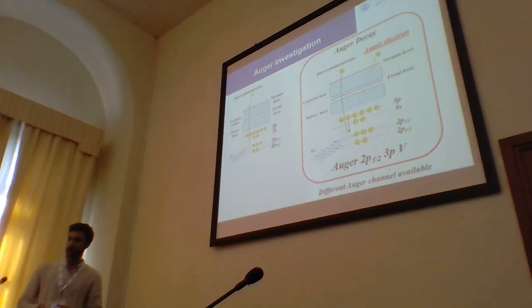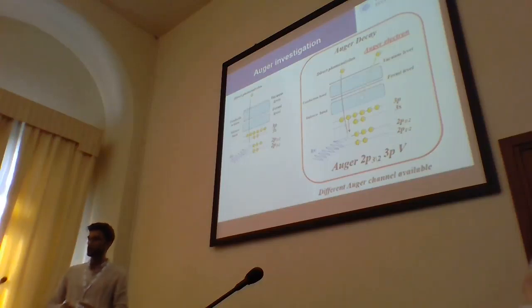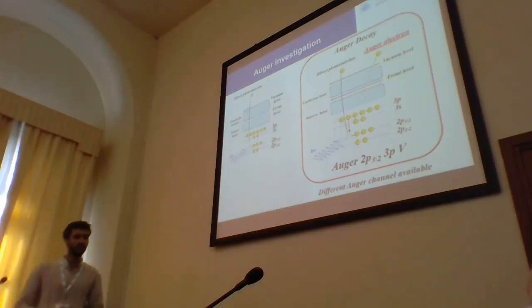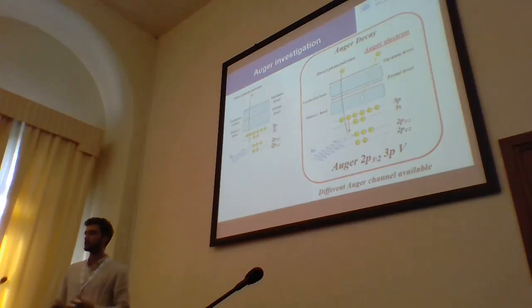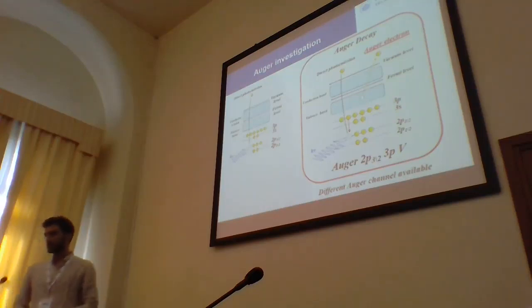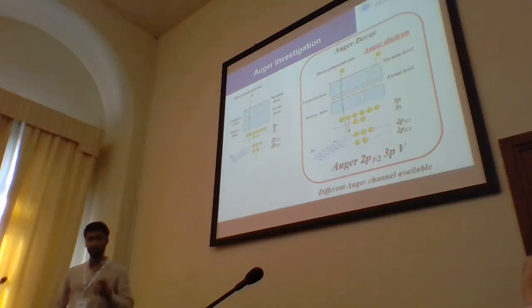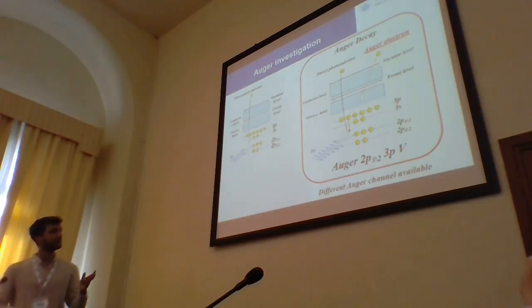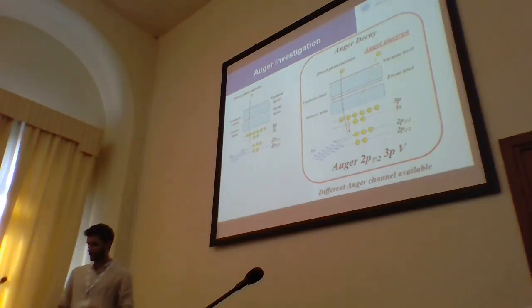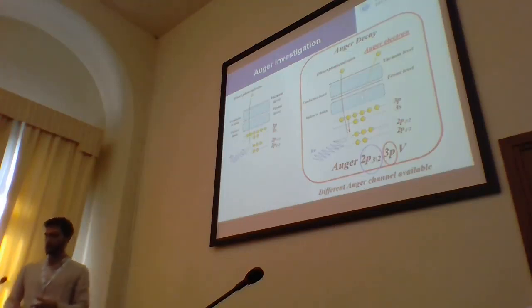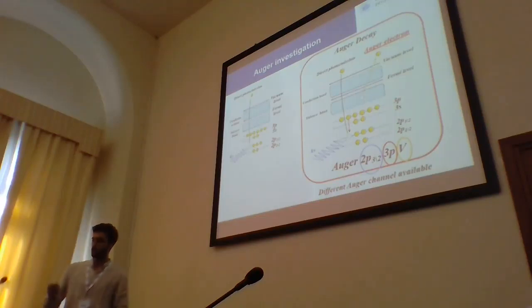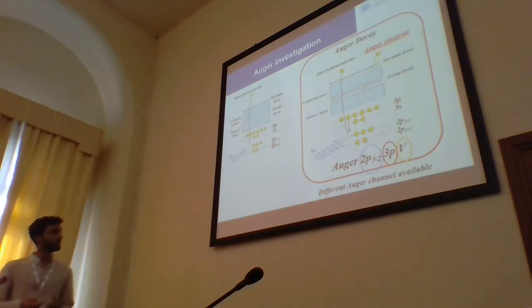So the Auger decay is a particular kind of photoemission process, which is the consequence of direct photoemission. With direct photoemission, we create a hole in a core level, and the system, of course, is not stable, and a surrounding electron will try to cover this hole. So, for example, in this picture is depicted the Auger decay 2p 3/2, 3p, and valence, since we have the direct photoemission hole in the 2p 3/2 level. Then the electron that will cover this hole comes from the 3p level, and the proper Auger electron will be ejected from the valence band. So, following this decay channel, we can actually probe the valence band.